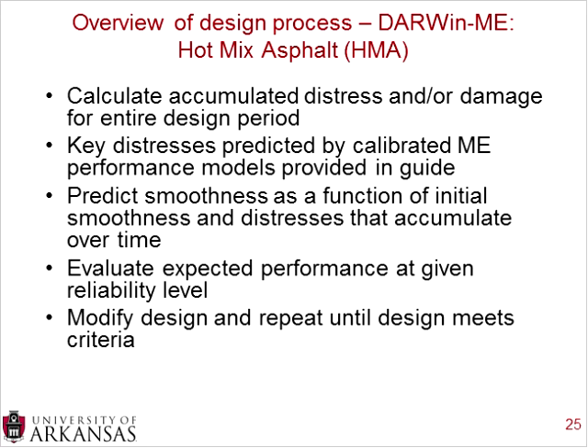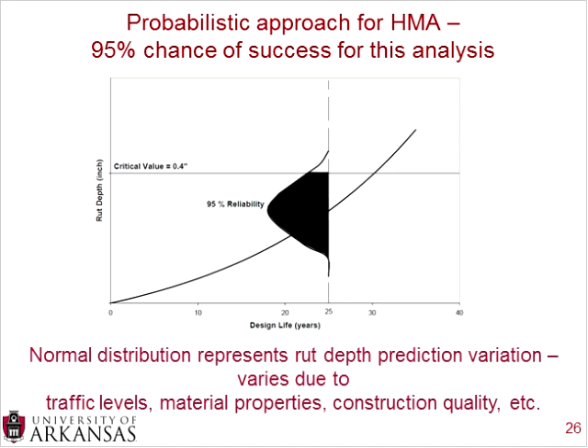So it's a real broad overview. Both Portland cement concrete and hot mix asphalt, you enter in the material properties and the site properties. You enter in the traffic environment. You put those into the DARWIN-ME program, and then the distresses and damage comes out of the program. And you say, is this an acceptable amount of distresses and damage? If it is an acceptable amount, then you have your design. If it's not an acceptable amount, then you need to modify your design and repeat until it meets criteria.